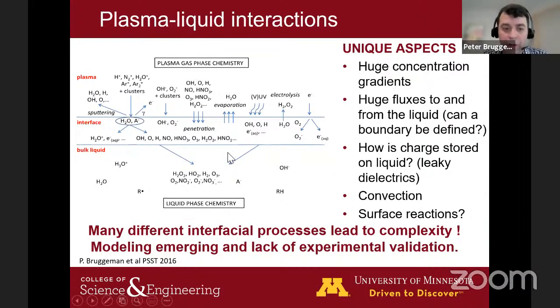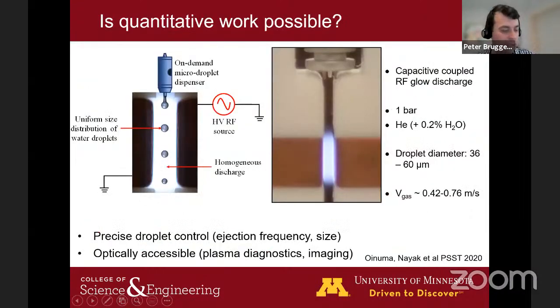And then ultimately, if the process is really happening in the liquid, you still fully need to understand how these species are being transported. Because many of these species are short-lived, you basically have a boundary layer of the liquid that is extremely important in that process. That could be tens of nanometers to micrometers in size. That is almost impossible to probe experimentally. And the conditions there are highly unknown and might actually impact a lot of the things we are trying to do. Now, our lab is always trying to do very simple things to enable us to draw stronger conclusions than looking at very complex systems.